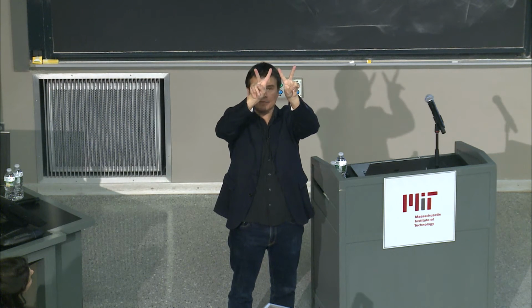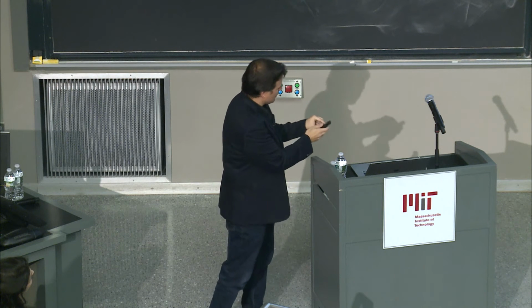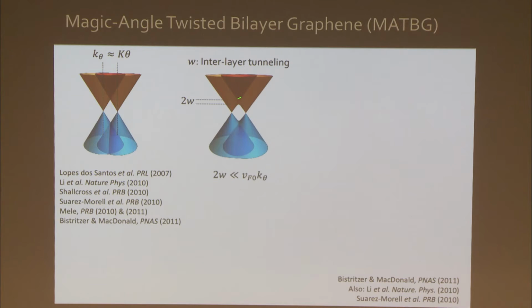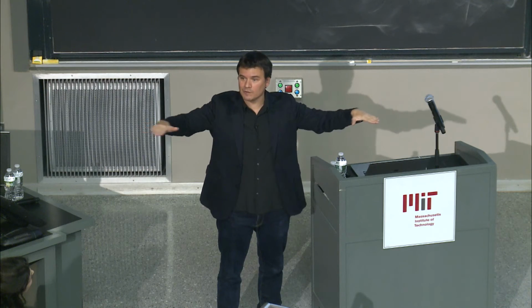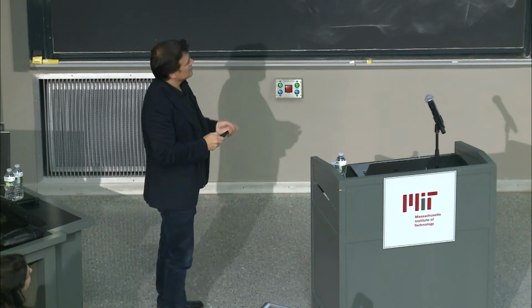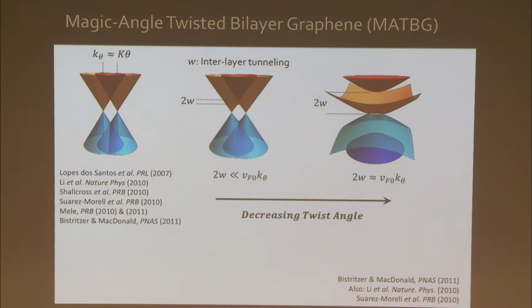These two Dirac cones get closer and closer to each other, and that crossing point pushes one of these bands down in energy, because of the band gap opening. They get closer and closer, and it pushes it to lower and lower energy until it reaches 0. At that point, we say that a flat band condition has been realized, and it occurs when this interlayer tunneling is roughly the same as the energy of that crossing point.